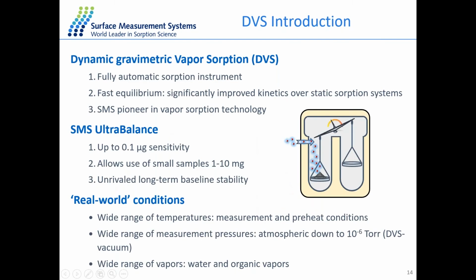In general, DVS, dynamic vapor sorption, is a kind of gravimetric method. You measure the change of mass for the sample at different concentrations of moisture or organic vapor. And we have different configurations of the balance, which allow you to put as little as 10 milligrams of sample, or up to maybe 5 grams of sample, depending on the configuration of the balance you use. For the experiment conditions, we can perform the experiment at real world conditions, at ambient temperature and pressure. And we also have the vacuum system, which allows you to degas the sample under vacuum and perform the experiment under vacuum as well.